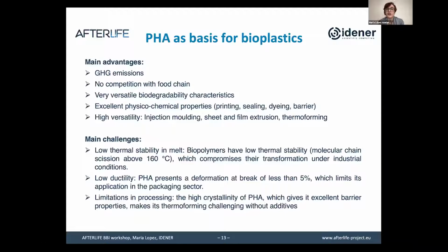So even with these advantages, we have some technical challenges before the application of the PHA in the production of bioplastic materials. The first one is that the PHA has a very low thermal stability, because the polymer starts to degrade at 160 degrees. So it compromises the transformation within the industrial processing window.